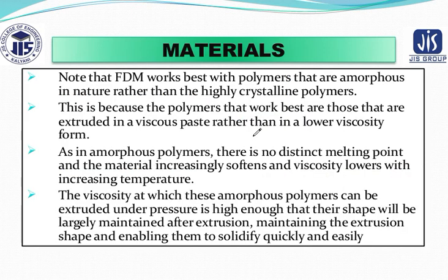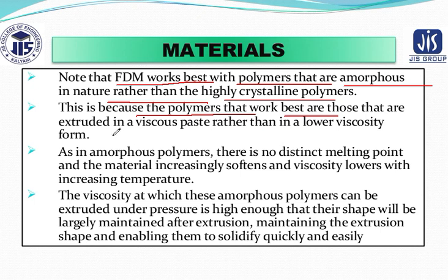Now materials. Basically, FDM works with polymers that are amorphous in nature rather than highly crystalline polymers. This is because the polymers that work best are those that are extruded as a viscous paste rather than in lower viscosity form. If it is a viscous paste, then the deposition rate is also very good. It is controllable and the flow rate is also very effective.